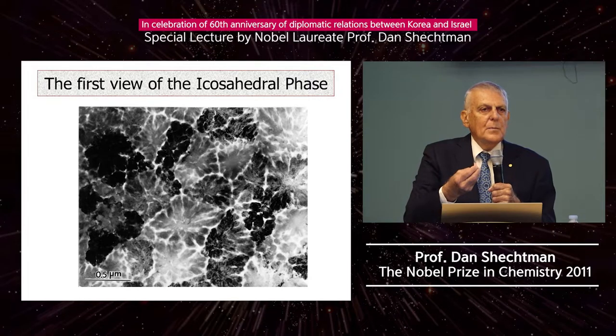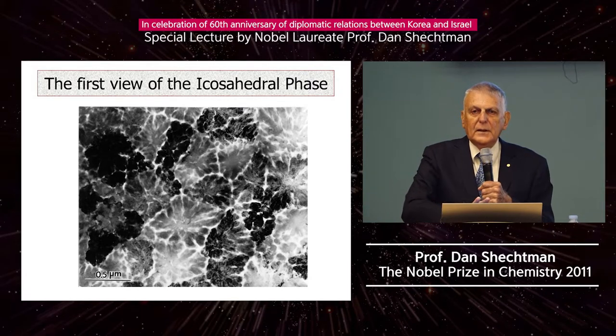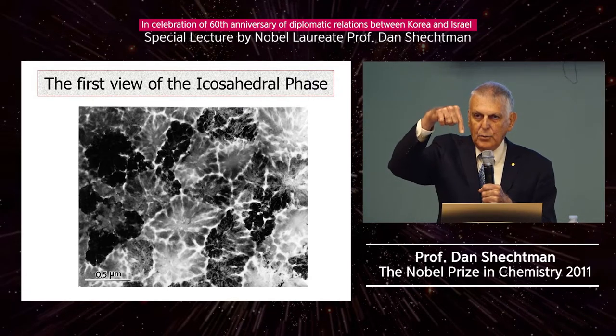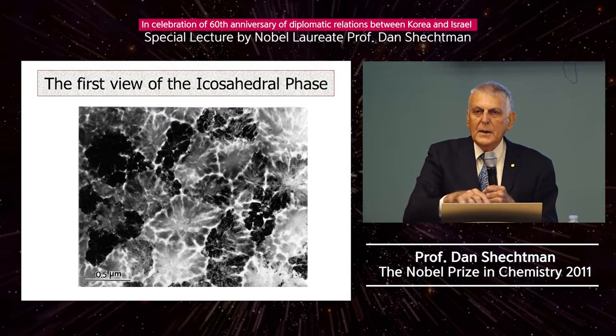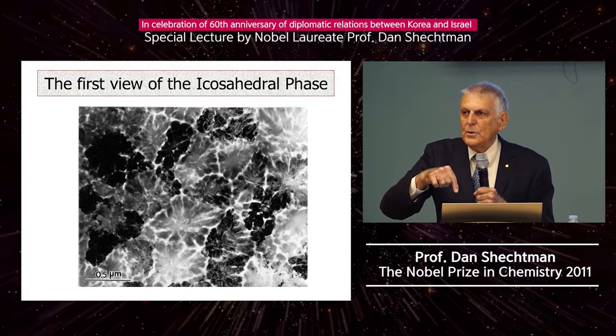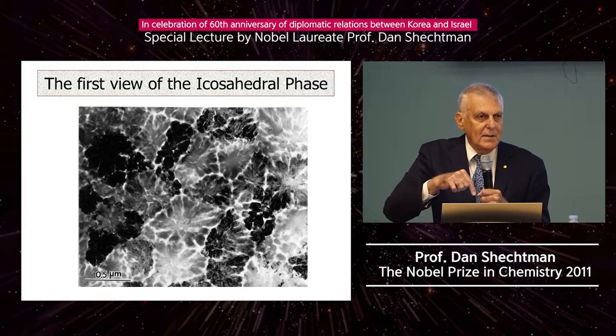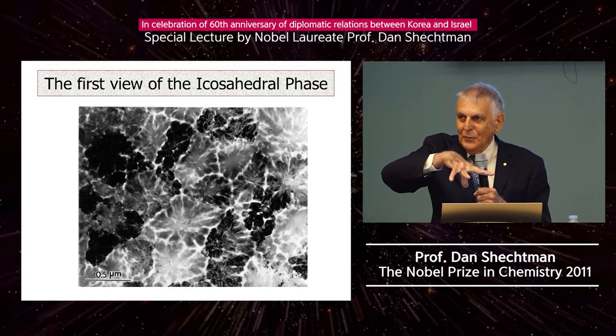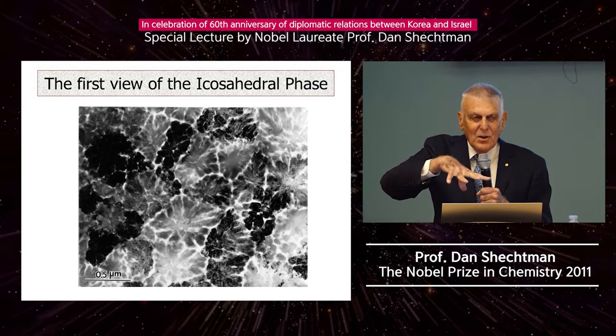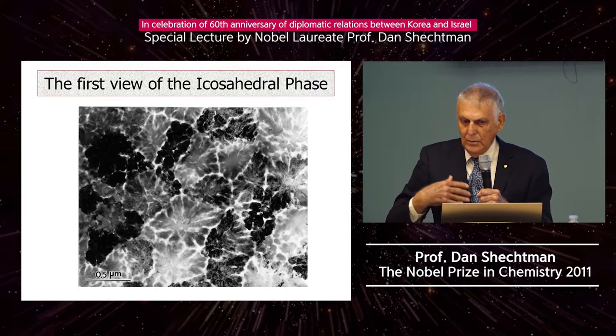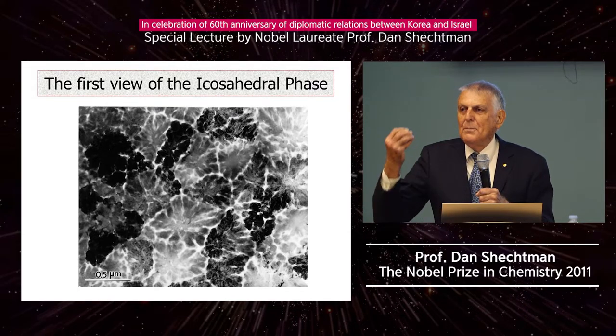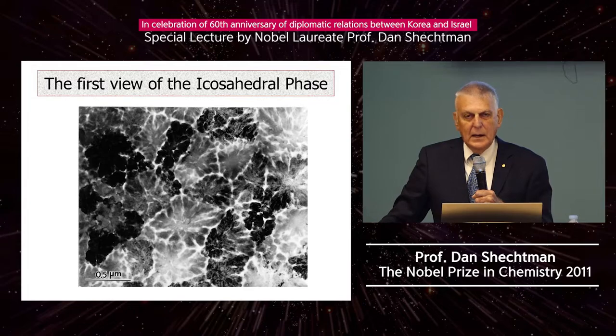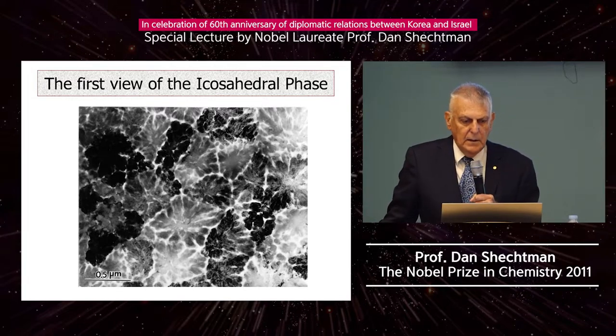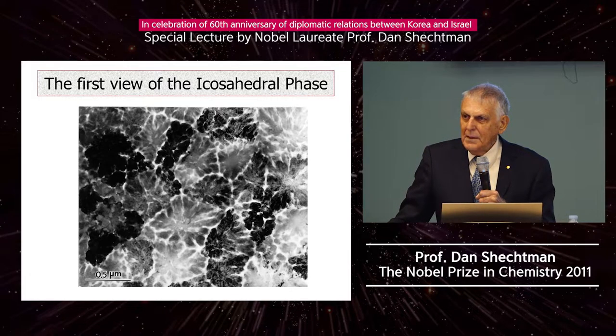When a crystal is pitch black, and this is a bright field image taken through the transmitted beam, it means that the transmitted beam has almost no intensity. So where did the intensity go? It goes to the diffracted beams. So I have never seen before that date such a black crystal in my career. And I was a veteran of electron microscopy. I was pretty good at it. And I said, that's interesting.